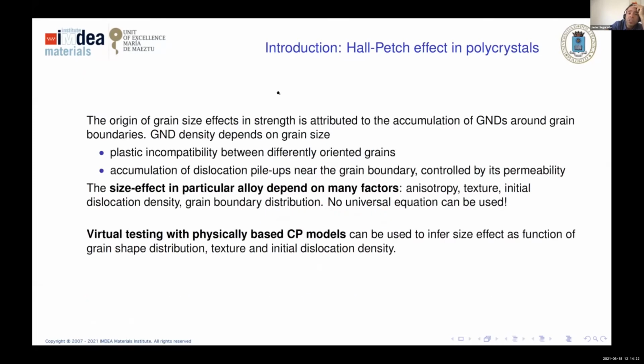Okay, first, which is the physical origin of grain size effect? It depends very much on the particular alloy, but one of the most common mechanisms that give rise to size effects is the accumulation of geometrically necessary dislocations around grain boundaries. Okay, and these geometrically necessary dislocations appear due to the plastic incompatibility and the accumulation of dislocation pileups near grain